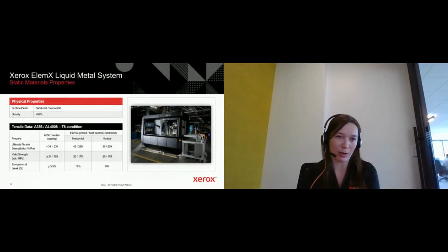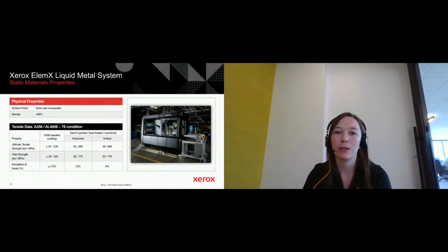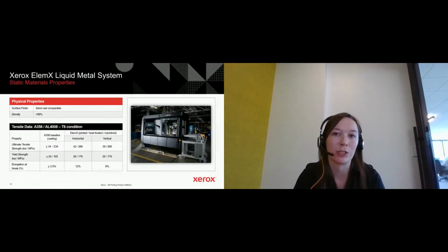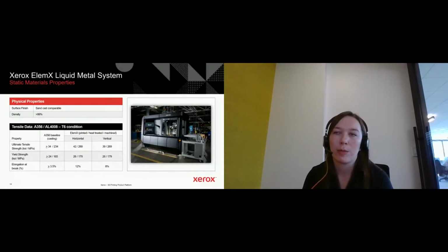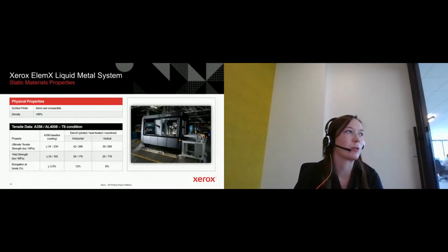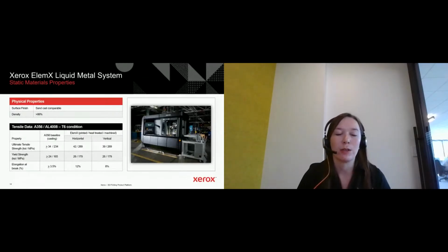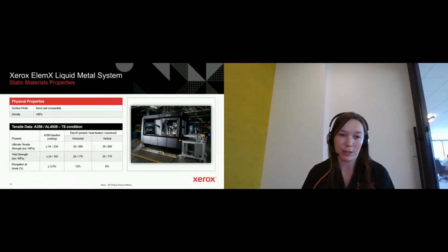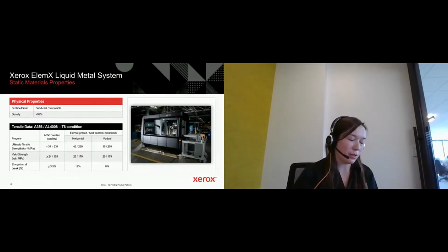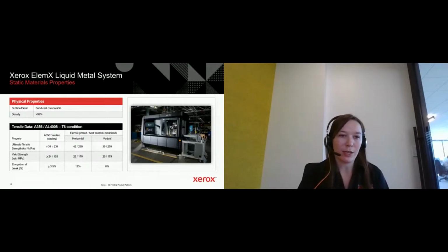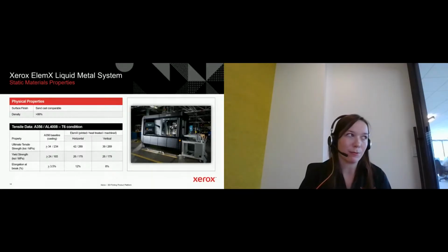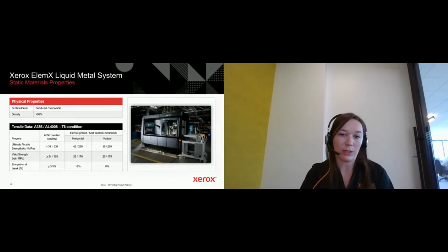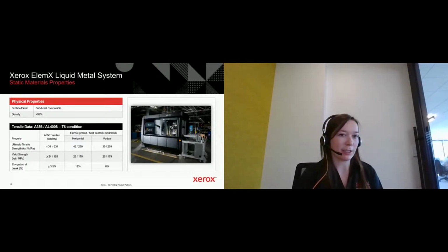So as far as mechanical properties and physical properties, I would say that the surface finish is sandcast comparable. It's not the smoothest surface finish, and if you have critical mating surfaces, you might still have to machine those surfaces. But I think it is a pretty standard kind of surface. And then our density is greater than 99%. You guys are probably aware there's some nuance with regard to density measurements, whether you're using Archimedes or CT scanning or image analysis, and they all agree that it's above 99% or 99.5, which I think is great for a technology that's really only been around for just barely 10 years.